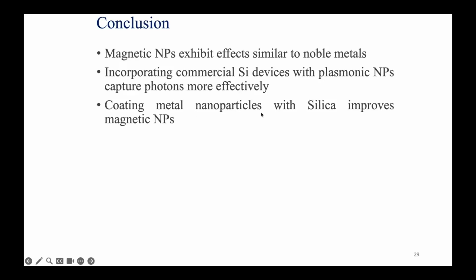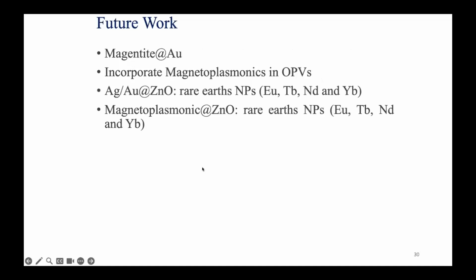So my conclusion is that magnetic nanoparticles also exhibit effects similar to noble metals, and incorporating them in commercial devices with plasmonic nanoparticles captures photons more effectively. Coating them also improves the magnetic nanoparticles. Now what we're trying to do is take the magnetite and coat it with gold nanoparticles instead of just having the gold nanoparticles, and also incorporate gold or silver nanoparticles inside zinc oxide, and use rare earths.